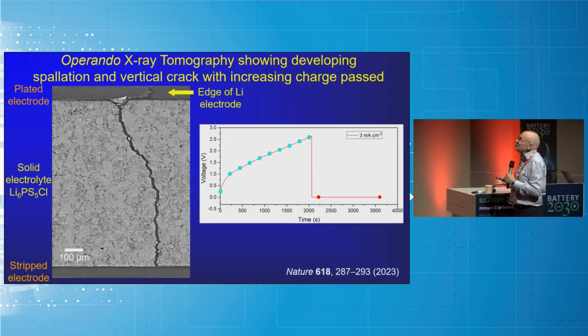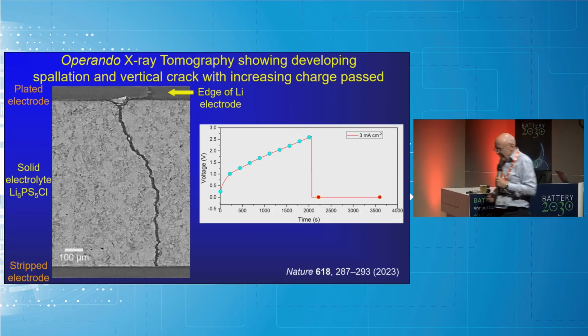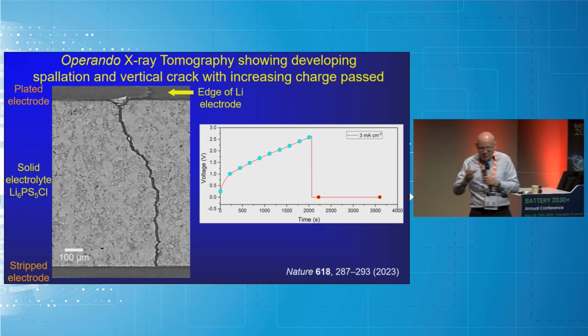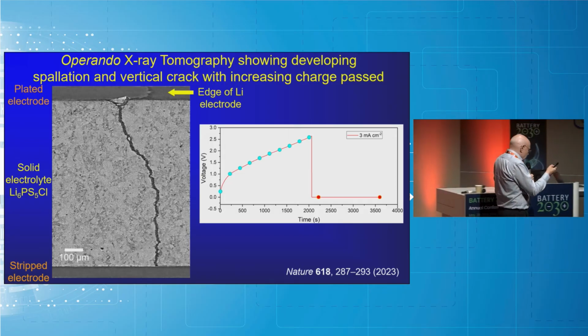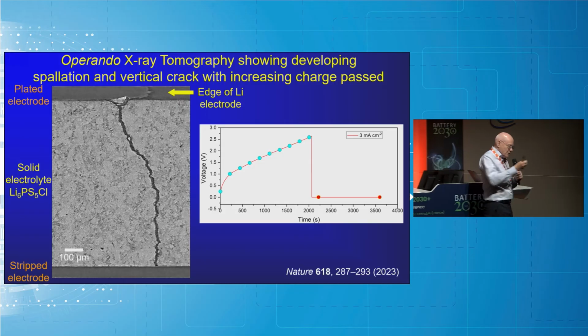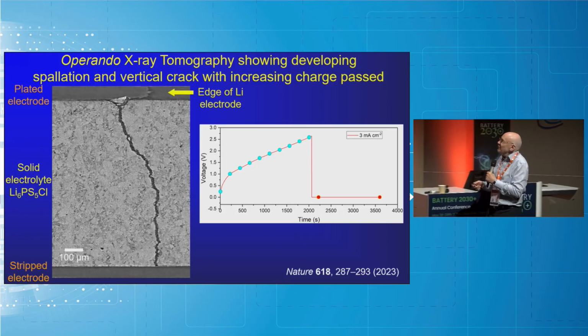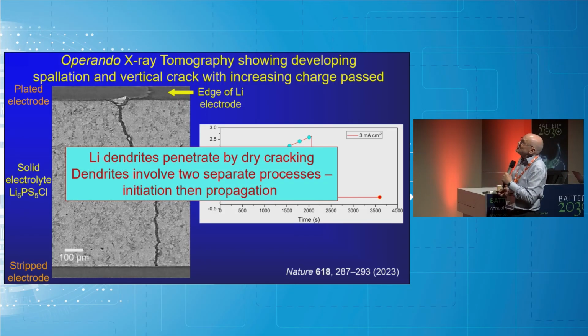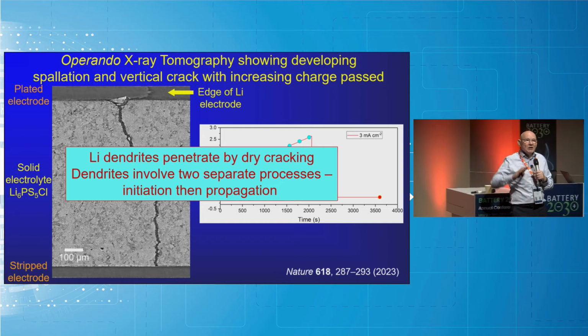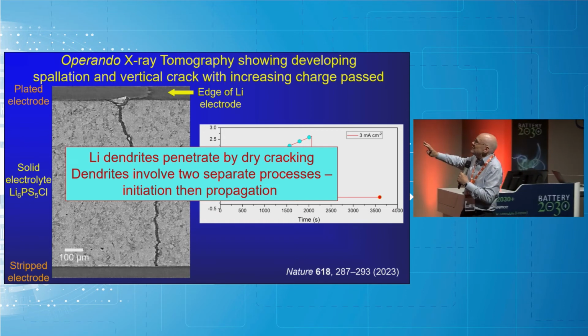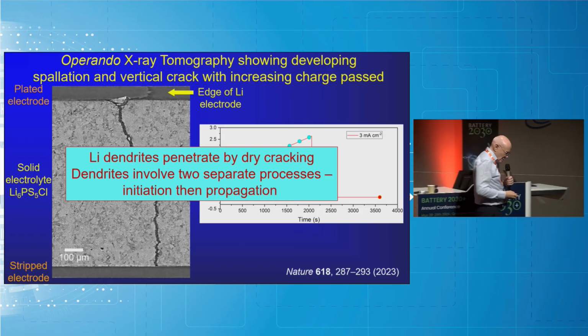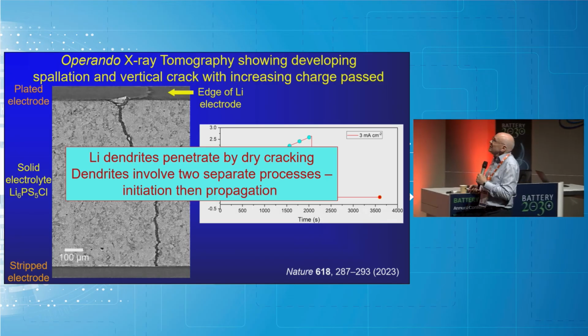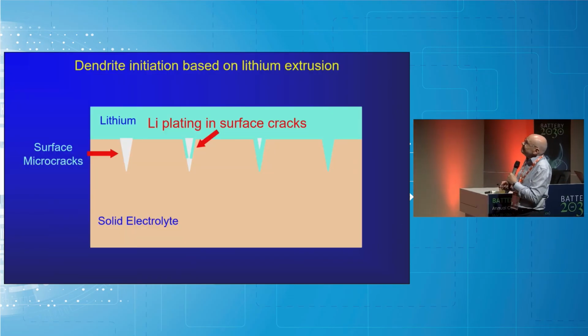So what this told us is that most of the models for dendrites had assumed the lithium was driving the crack in the ceramic at the tip. This suggests that isn't the case, and in fact we have to consider the dendrite process in two parts: the initiation of the dendrite and then how it propagates. Now I don't have time to talk about the propagation today. I'm just going to focus on the initiation part, but we've modeled both these phenomena.